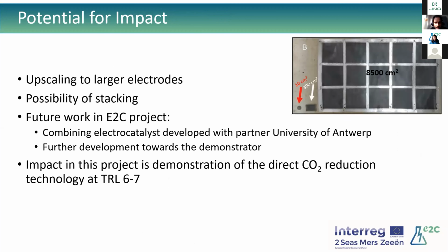the potential for impact, what we will do in the near future is looking towards making these electrodes larger. In the graph, you can see in red a 10 square centimeter electrode, which is the typical size of the experiments we are doing. Then next to that, you see a 300 square centimeter electrode, which is a bench scale setup, which will be used and is being used in this project. On the right, you see even a much larger segmented gas diffusion electrode, which will not be used in this project, but at least it's just to show that larger areas are possible.